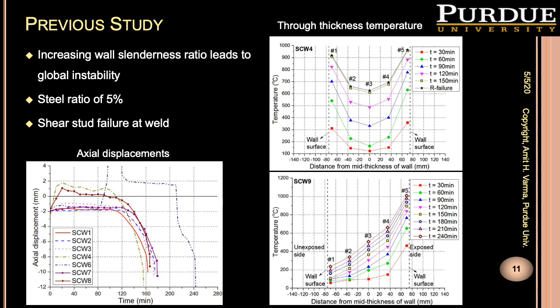And here you're looking at the axial displacement versus time curves for specimens 1 through 8 that were subjected to uniform heating. What you'll notice is that a lot of the axial displacement versus time curves are clumped around the same time interval of about 160 minutes, with the exception of one specimen that seems to have a behavior that's a little bit different, going all the way up to 240.